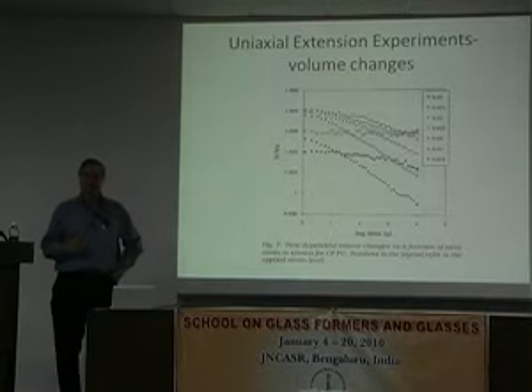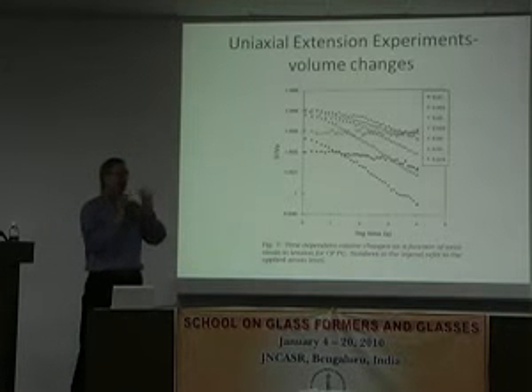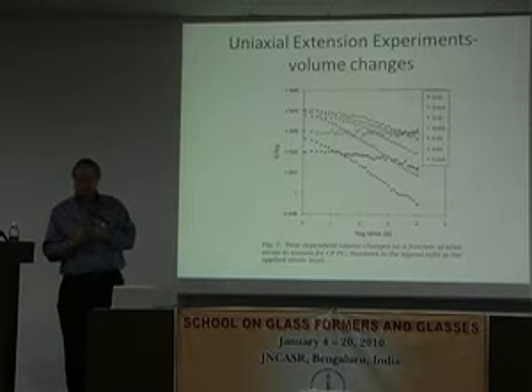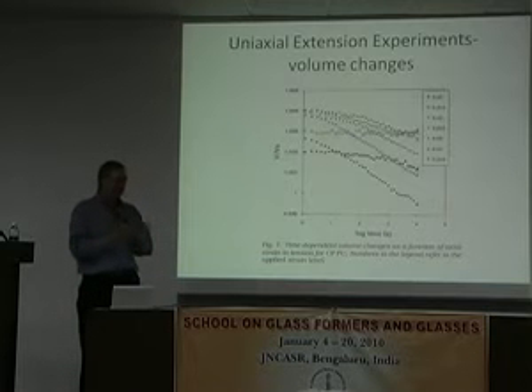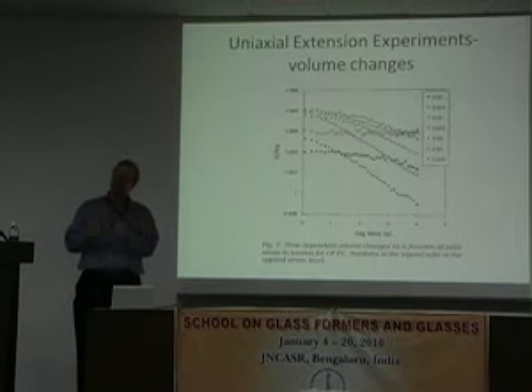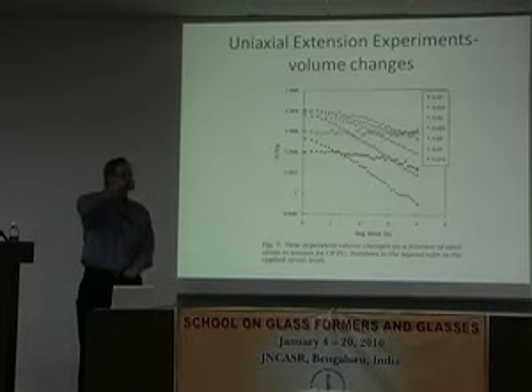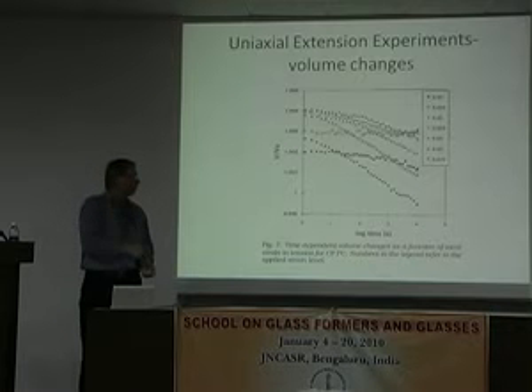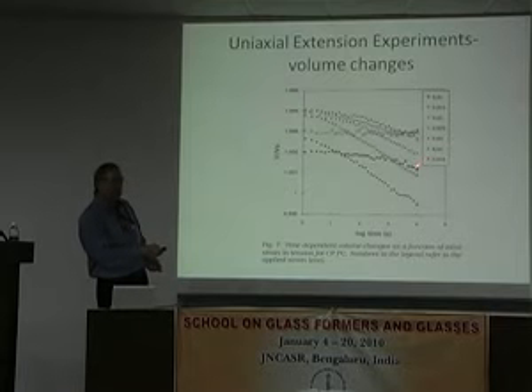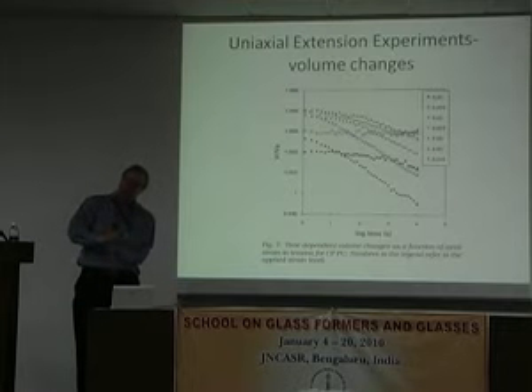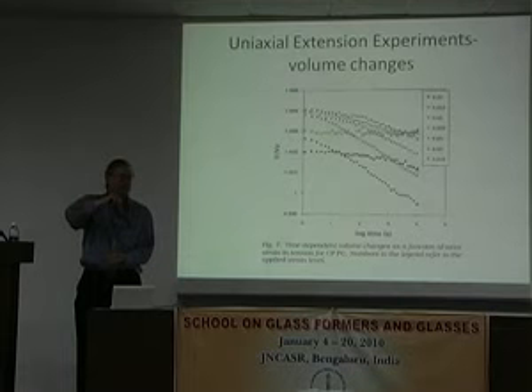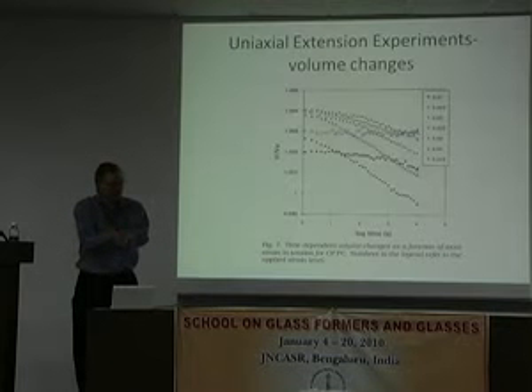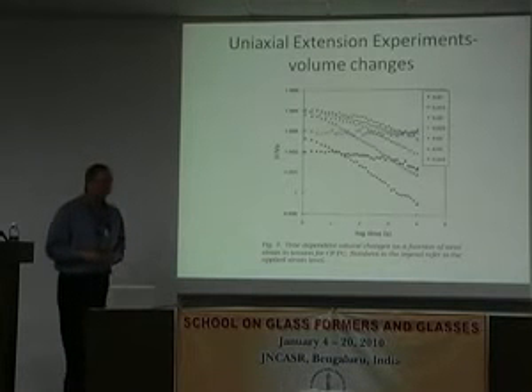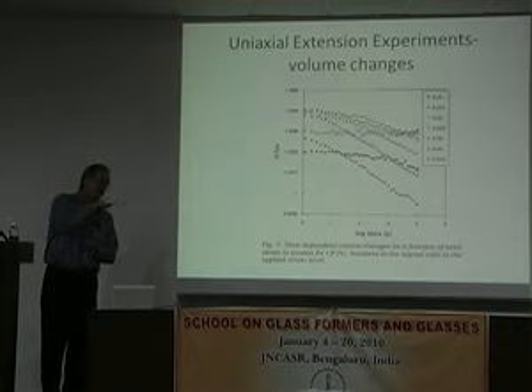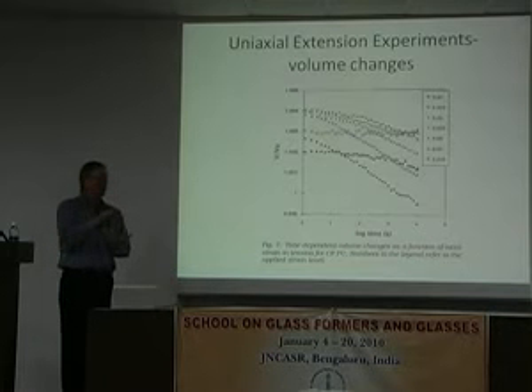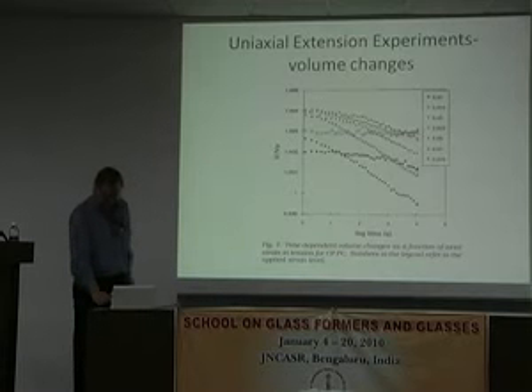Now, admittedly, I have no real idea why this happens. We can talk about why it might happen. Obviously, I have a material that's out of equilibrium. And in this case, I perturbed it rather strongly. 4.5% is not quite to yield, but it's getting up there. So I perturbed it quite strongly, and now the material really does want to recover towards its equilibrium state. And this might be more like that shear of a colloid that you're seeing, where you really increase the mobility. So that's what we call implosion.